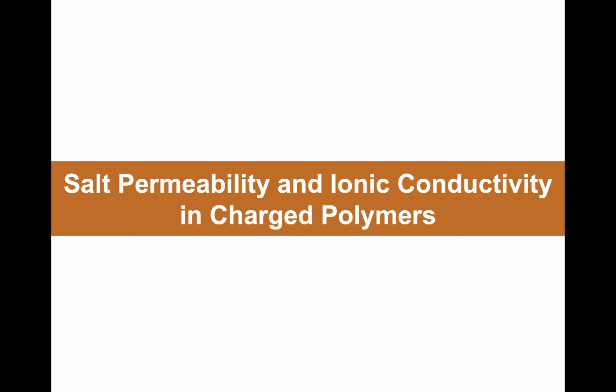And in the first part of this lecture, we talked about the so-called Donnan model for ion sorption into charged polymers. We showed how that model typically fails, and we identified what we believe is the basis for that failure, and that is the fact that historically people have not properly accounted for activity coefficients, thermodynamic activity coefficients of the ions in the membrane, and in some cases even in solution.